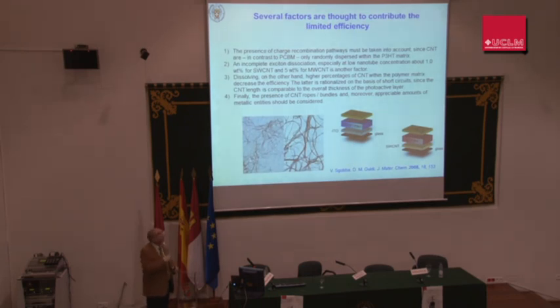Probably it is because there is still no very good method to prepare pure single wall carbon nanotubes. When you get carbon nanotubes, you have different diameters, different lengths, different chirality, different electronic behavior, metallic versus semiconductive and so on. When you have metallic carbon nanotubes, consider that the length of the carbon nanotubes is roughly the same as that of the active layer. That means that you get a short circuit, and therefore there is no efficiency.